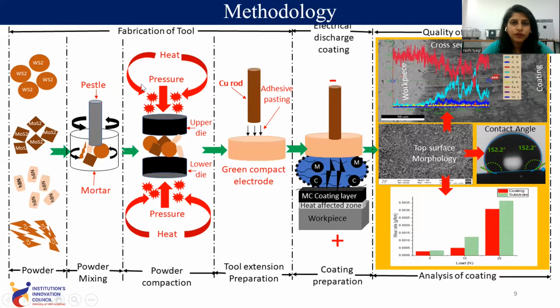Initially we fabricated the green compact tool, then we performed the electrical discharge coating, then we analyzed the quality of the coating. Basically, the tool is fabricated by using different powders. This is the powder that we have used. We mixed this powder in a mortar and pestle. After the powder mixing, we compacted it in the hot mounting press, which is basically used to compact the powder.